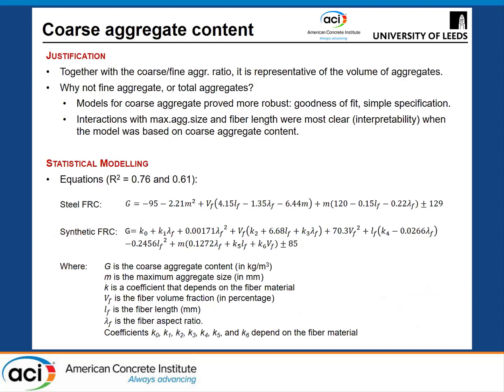Then, after looking at the coarse to fine aggregate ratio, it was also important to look at the total aggregates content. And rather than the total aggregates content, it worked better from the point of view of regression analysis, in terms of producing more stable results, more robust models, to use the coarse aggregate content. And again, a regression equation was fitted to try and obtain the coarse aggregate contents as a function of the maximum aggregate size and the properties of the fibers in terms of their sizes and so on.